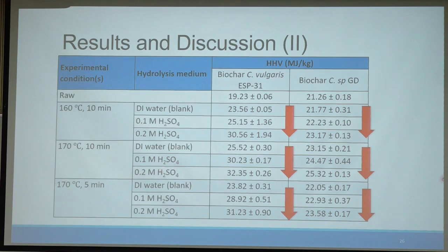But we can see that for the carbohydrate-rich microalgae, the increase of the HHV is lowest compared to the other species, C. sp GD. This one only increased from 22 to 23, a very small percentage, while the other species increased close to 50%. Better fuel properties.